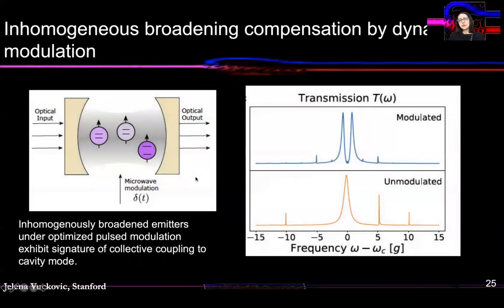Moreover, if you do full optimization of the microwave driving, you can even use the same effect to compensate inhomogeneous broadening of the system by dynamic modulation. I told you at the very beginning of this part of my talk that the main issue with using color centers or spins in semiconductors to build scalable quantum systems is achieving all qubits to be the same, because they're heavily influenced by the local environment. And if you would like to compensate for errors between qubits or inhomogeneous broadening, you would need to tune each one of them separately. That makes the problem quite complicated.